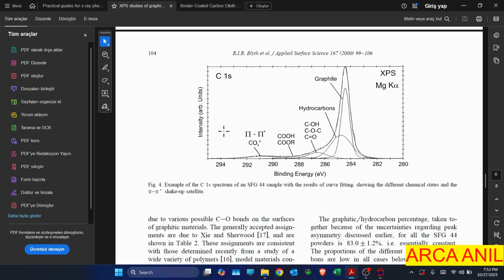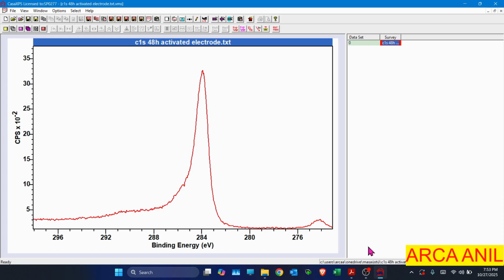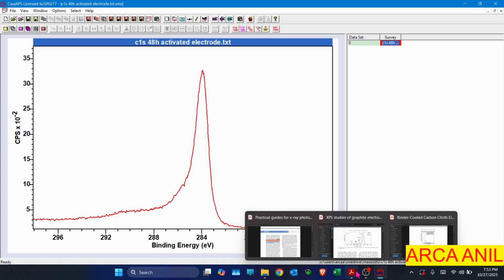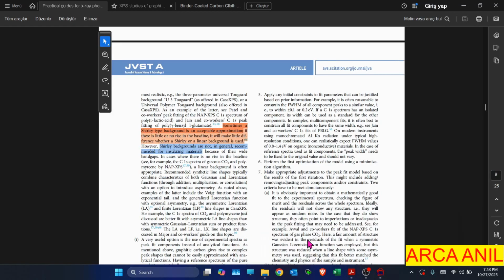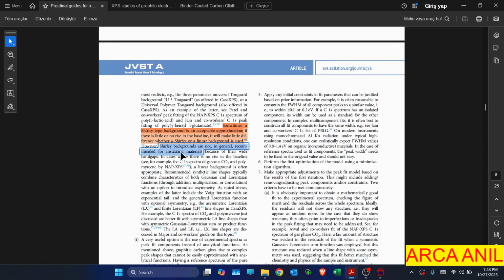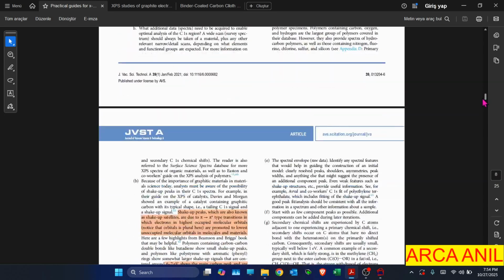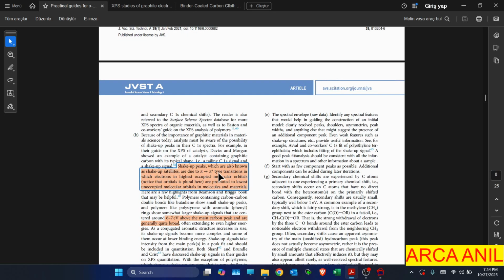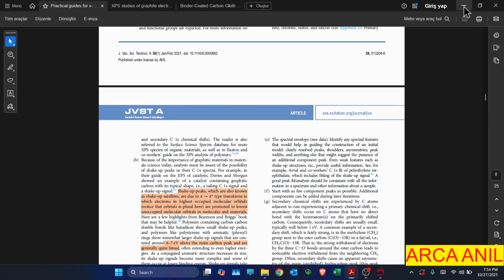And I want to make this kind of peak fitting for our sample. By the way, which background should we use? Therefore, I want to show you another resource here. This is the third paper. We can use the Shirley background for the carbon 1s peak fitting. Shirley backgrounds are not suitable if the sample is an insulating material, but this is not the case. Our sample is an electrode and it is very conductive. We should see a pi to pi star transition or shake-up peaks, and we saw it clearly. And we can use a Shirley background according to this paper, and I will do that.